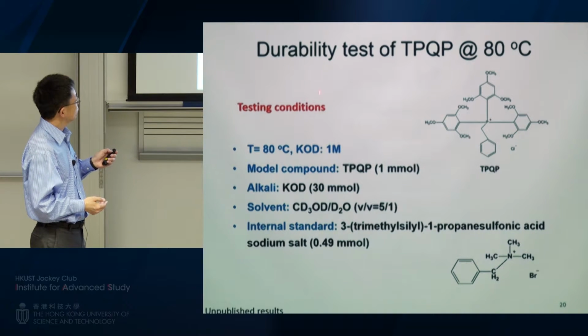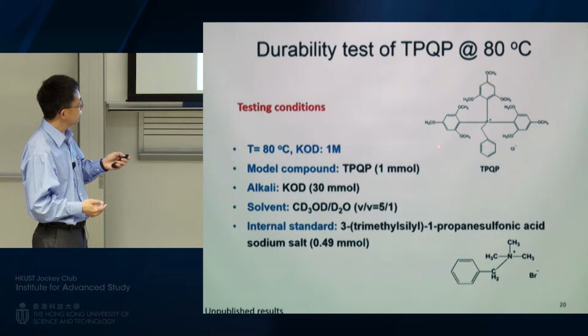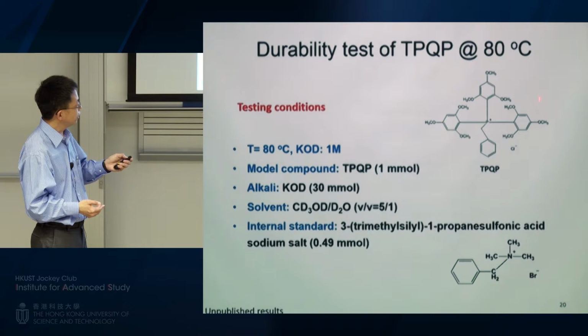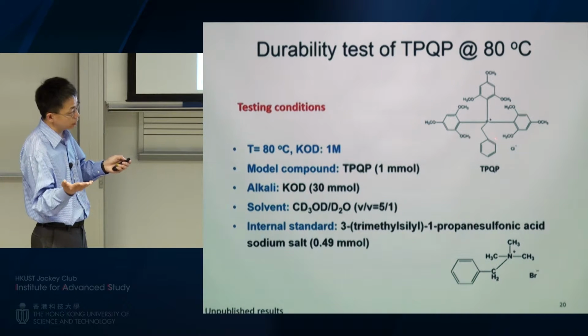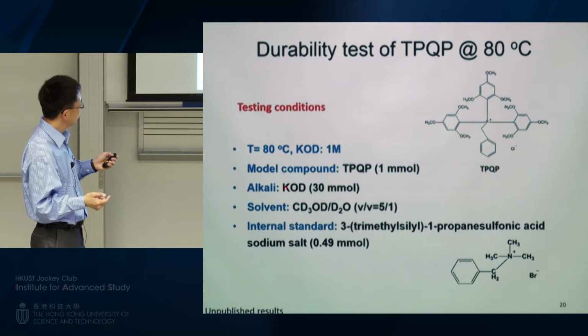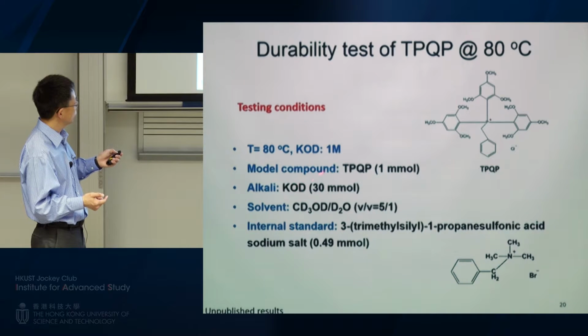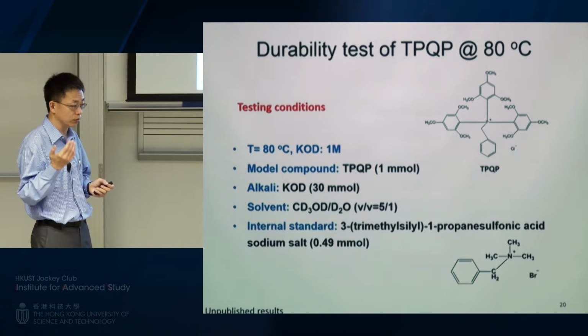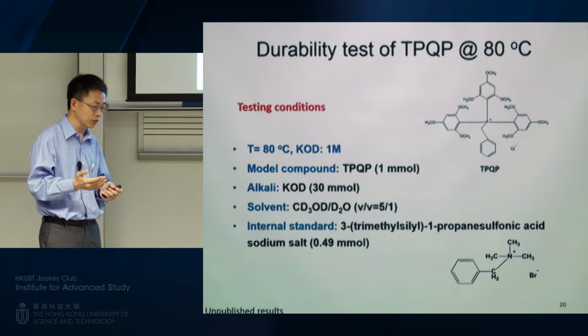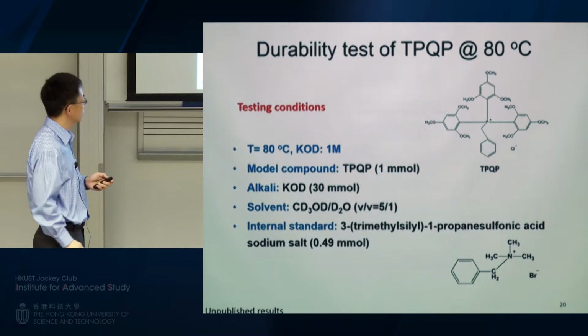So we do this in a test. It's 80 degrees C. We have this KOH, but now it's KOD because we need to do NMR. And we have this model compound. So instead of working with a polymer, we actually have this organic cation, just like the one shown in Jack's paper. And we have the base as KOD. And we usually have a lot of excess of the KOD versus the model compound because we want to make sure the basicity doesn't go down as the lifetime testing goes on.